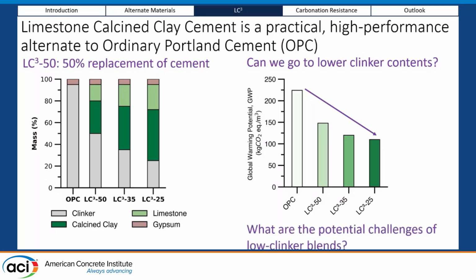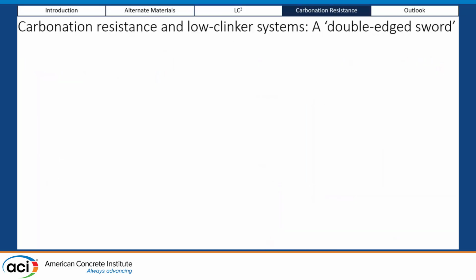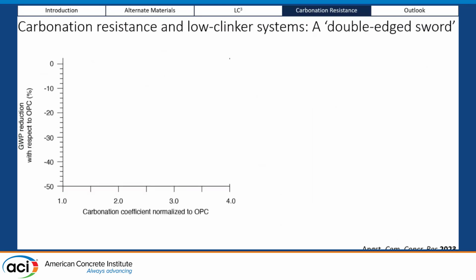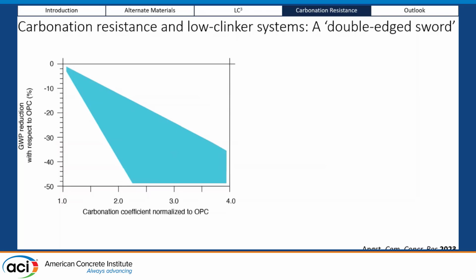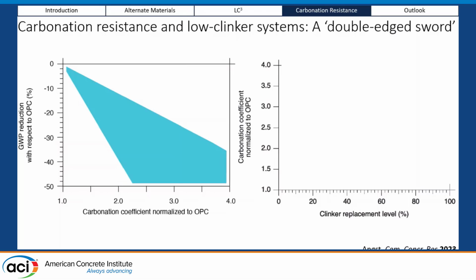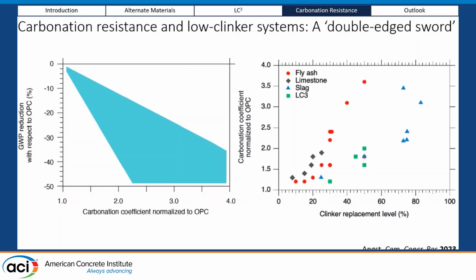So we are trying to figure out what other challenges these low-clinker blends contain. And one of the biggest challenges is carbonation resistance. In this curve, we see the reduction in the global warming potential on the y-axis and the carbonation coefficient, or the carbonation rate, typically in units of millimeters per root of time, normalized to OPC. As we reduce the global warming potential, which means we are either reducing clinker or building more sustainable blends, we are going right on the curve, which means we are increasing the carbonation coefficient. Similarly, if we continue to replace clinker, the carbonation coefficient keeps increasing. This is not desirable for various reasons.